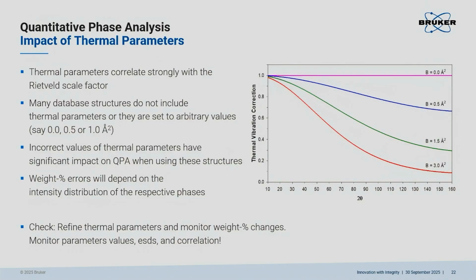If you have a problem with thermal parameters, for example, if you don't trust the values which you're using, refine them just for fun. You can rarely expect to refine meaningful thermal parameters from powder data, let alone in mixtures. But as soon as you see that your temperature factors start to change a lot, you have some sort of residual error in your data anyway. If that is correlated with your phase content, with the scale factors, then at least it is worthwhile to check the quality of the thermal parameters.